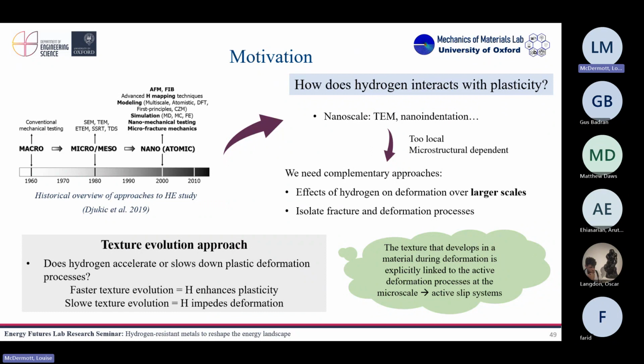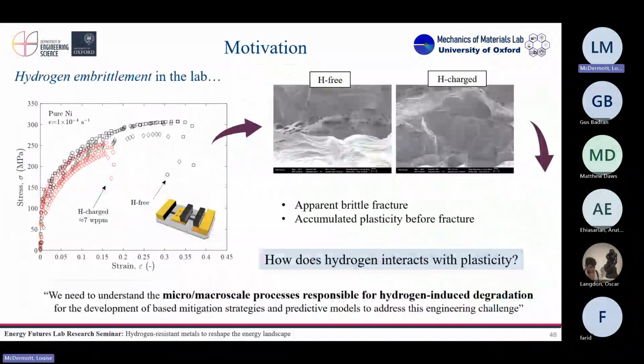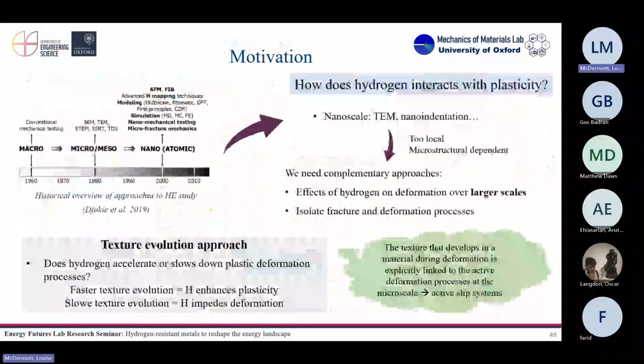Okay, so we wanted to overcome those limitations a bit and adopt a complementary approach that allows us to study the effect of hydrogen over a large scale. So let's say a sample size scale, and also isolate the deformation process from the fracture process. Because if you try to study something here, fracture is taking place, so it's very hard to isolate what's going on only during deformation. So we decided to adopt an approach that's based on studying the texture evolution of a material when you deform it with hydrogen inside.